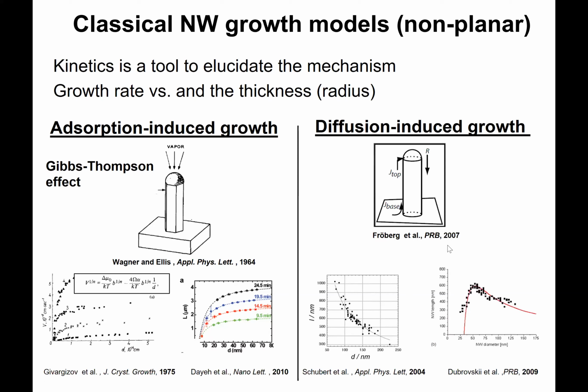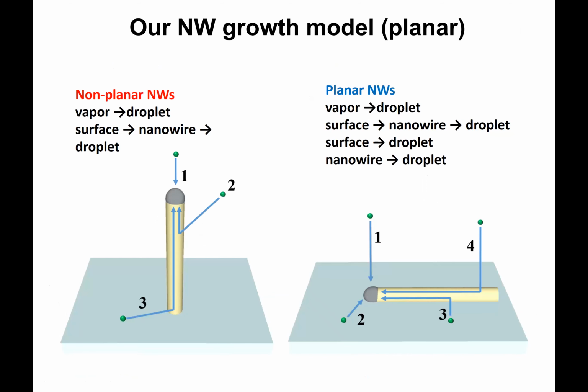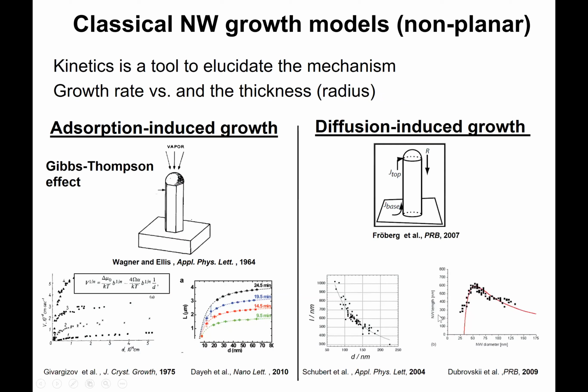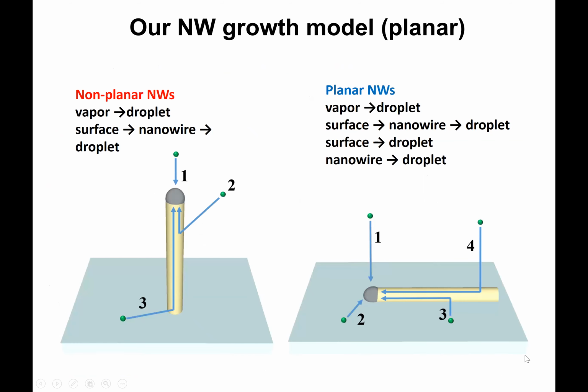And this is what gives this diffusion-limited dependence. This model that combines both the Gibbs-Thomson effect and the diffusion limitation was developed by Vladimir Dubrovsky at the Ioffe Institute in St. Petersburg. So what we did, and this was the work of a bright student in my group, Amnon Rothman...